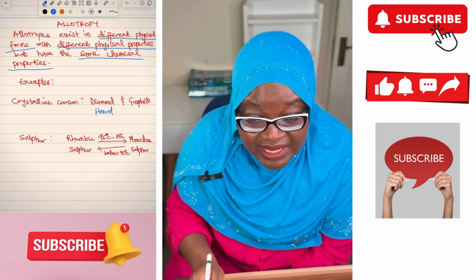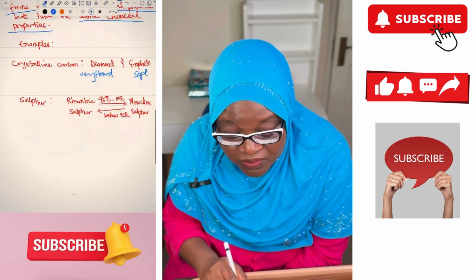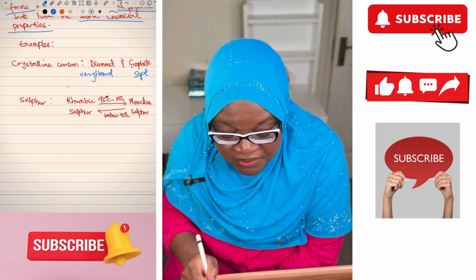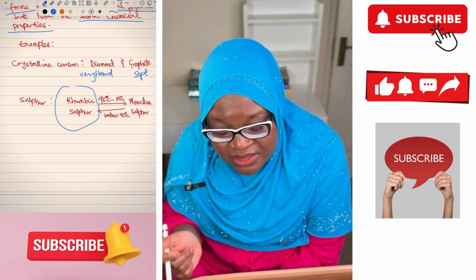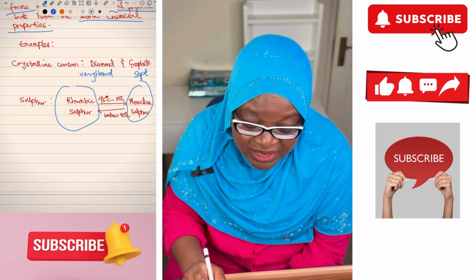Another example is sulfur. So I've highlighted two allotropes of sulfur. In fact, you can interconvert rhombic sulfur to monoclinic sulfur by just playing around with the temperature. If you subject rhombic sulfur to temperatures between 96 to 119 degrees, it gets converted to monoclinic sulfur. If you cool monoclinic sulfur below 90 degrees, you get back your rhombic sulfur.